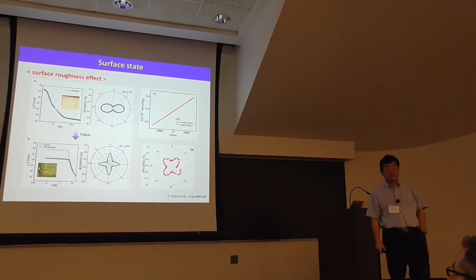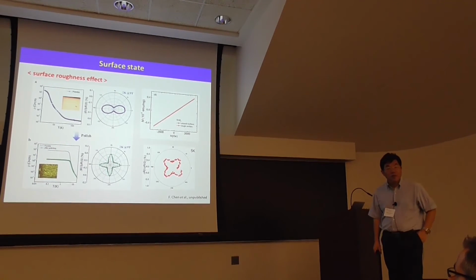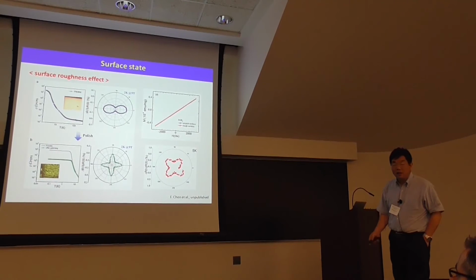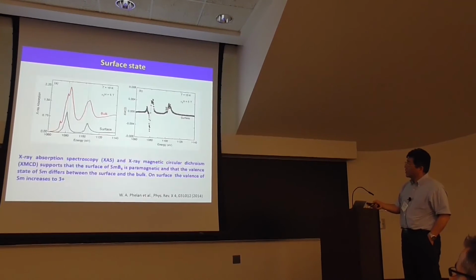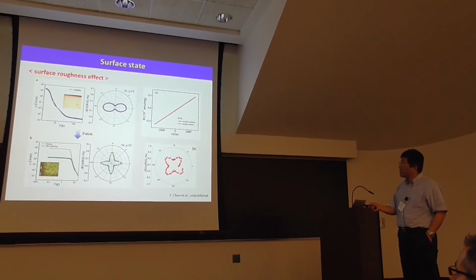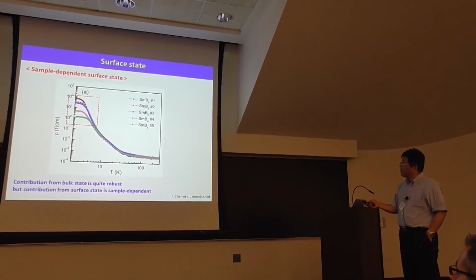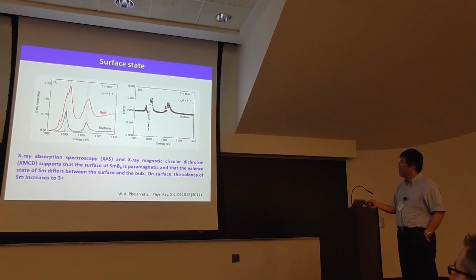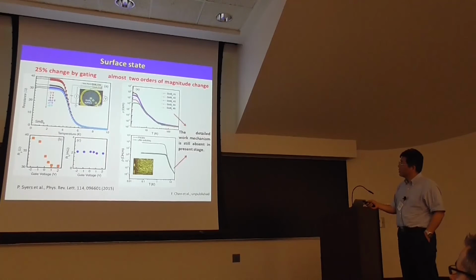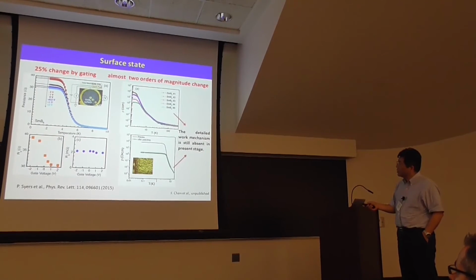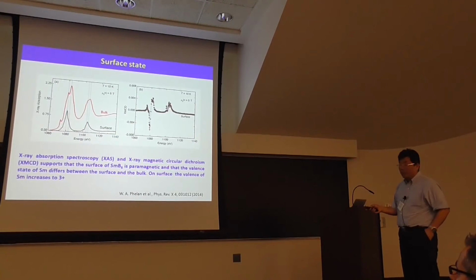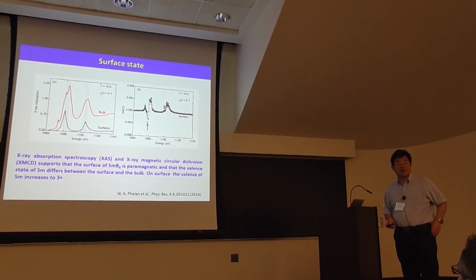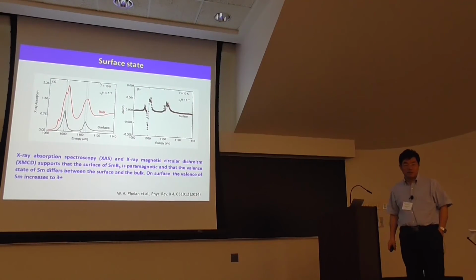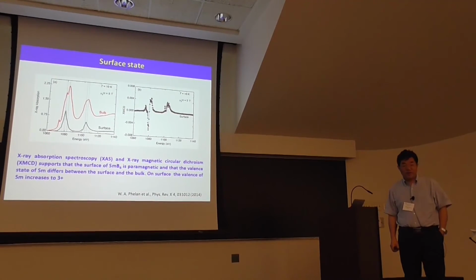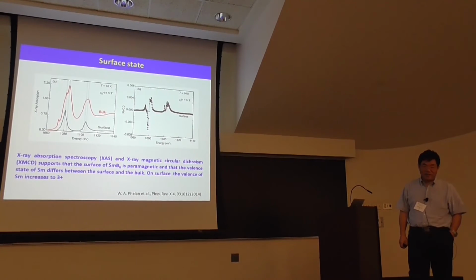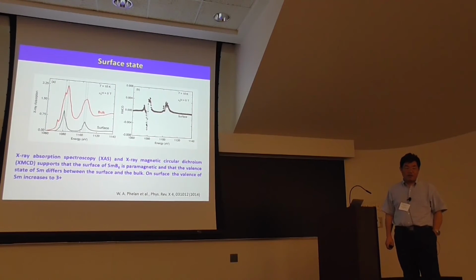What was the annealing protocol? How did you do the annealing? Which temperature and what atmosphere? We just annealed at 600 centigrade. You mean it's high, right? Well, compared to the melting point, it's not so high.